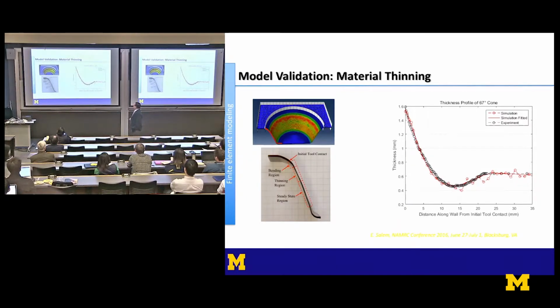What's even more impressive, given the simplicity of the constitutive law we put into this model, is that near the formability limit you actually get a thinned region when you start doing the forming, and it predicts that thinning quite accurately. That was something we knew we could make work, and in fact, we made it work pretty quickly.